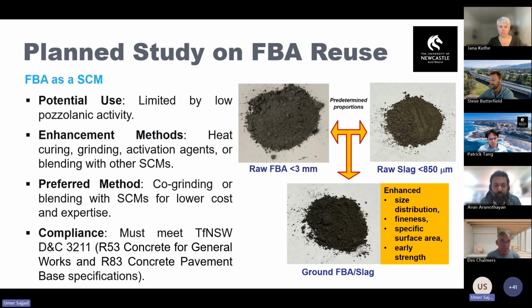And the preferred method, which we have opted, is the co-grinding or blending with SCMs for lower cost and expertise. In our case, we have used ground granulated blast furnace slag, and we have co-ground the furnace bottom ash with the ground granulated blast furnace slag. And then we replaced cement with that blend. In addition to that, we have replaced natural sand with furnace bottom ash. So we're working on the compliance with the Transport for New South Wales specifications, specifically R53 and R83.